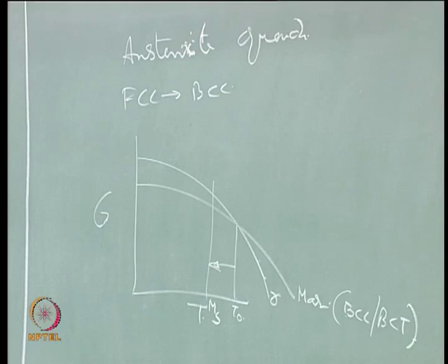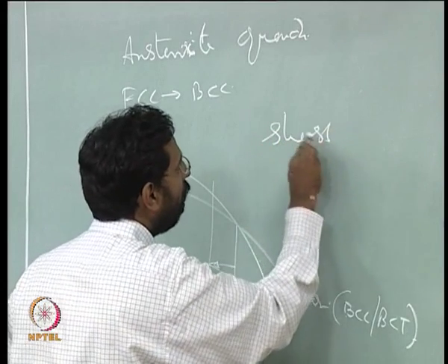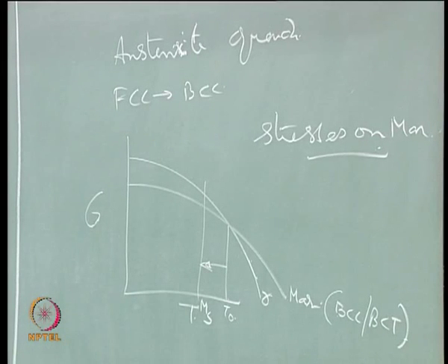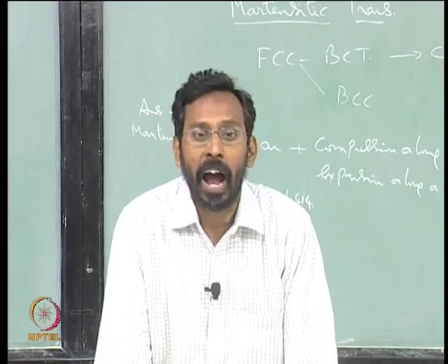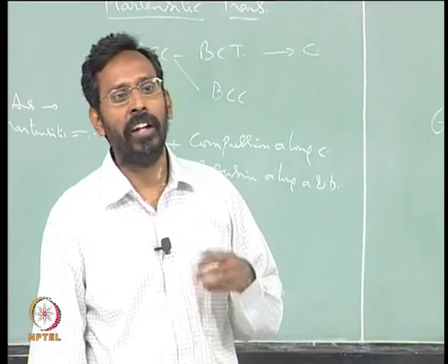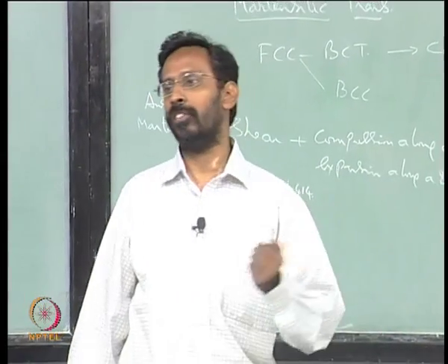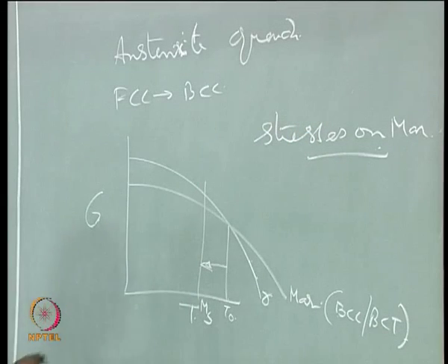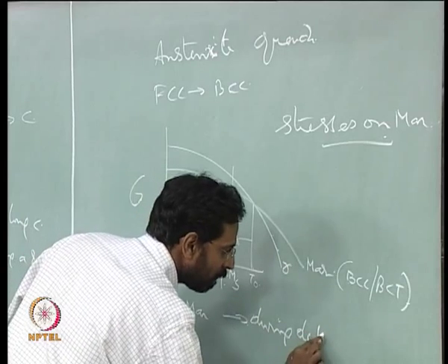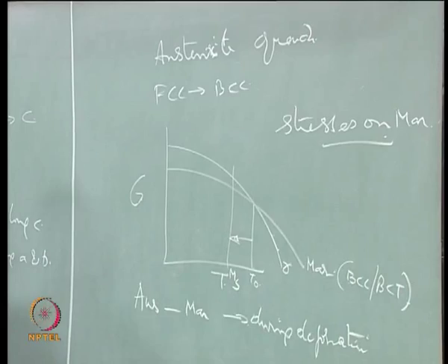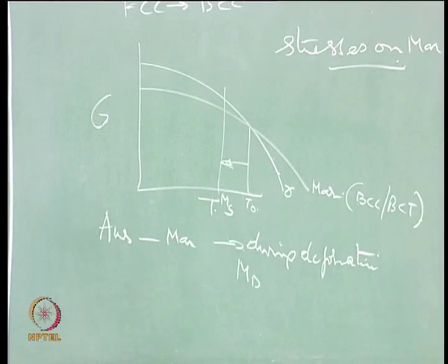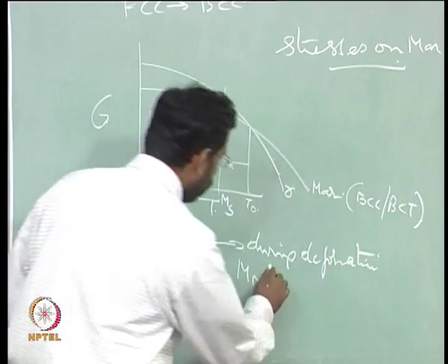This is where we need to understand the influence of stresses on Martensitic transformation. We always say there is something called stress induced Martensite. You have heard of it? Hadfield steels is one of the wonderful examples of it. You take an austenite and quench it and get the austenitic structure and deform it, and you would see during this deformation this austenite transforms to Martensite. This is what we call deformation induced Martensite, and we even give a temperature called MD temperature for the temperature where the Martensitic transformation occurs during deformation, and usually this MD is always greater than MS.